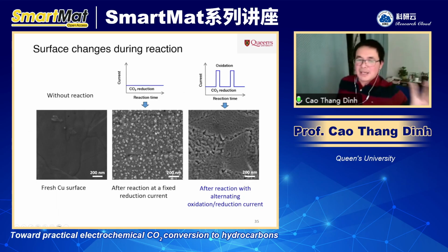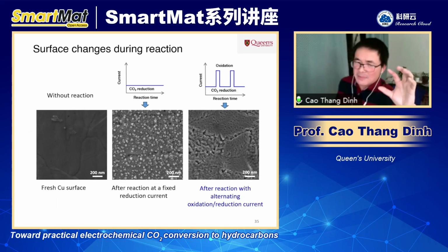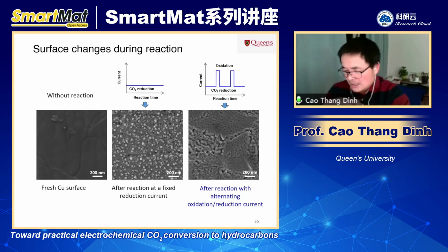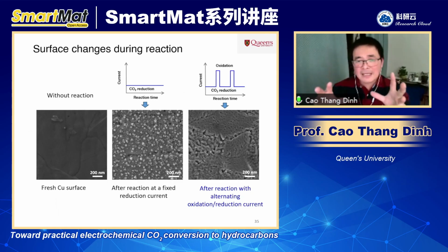We don't know the exact mechanism, but probably the copper reconstruction. But what we are quite sure of here is that on the surface of the copper, when we apply the alternating current between the positive and negative, it creates some kind of porous structure. So we think this feature of the copper is the key for methane formation, even though at the atomic level we don't know exactly what is going on, because we could not characterize them in situ here. But we think the methane is related to the surface of the copper.